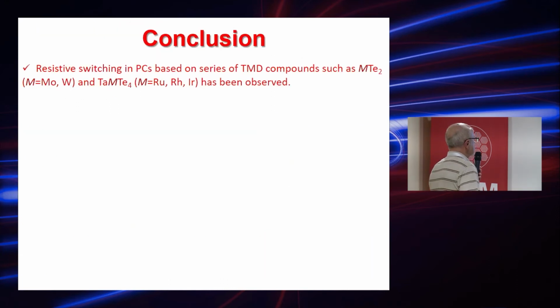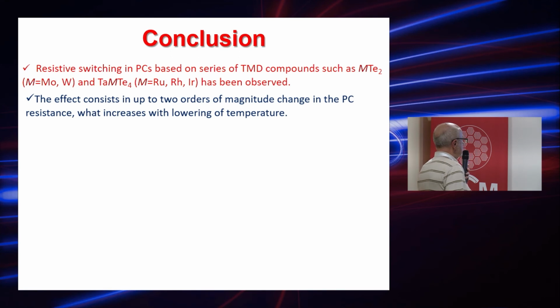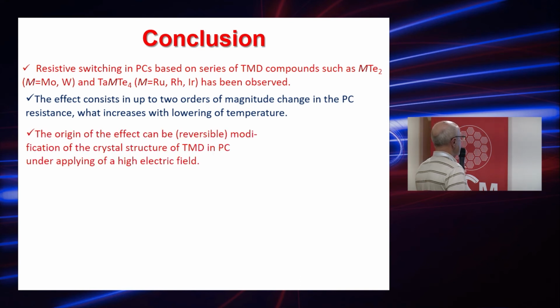So, in conclusion, we observed resistive switching in point contact based on a series of TMD compounds such as molybdenum and tungsten ditelluride and tantalum ruthenium, rhodium, or iridium ditelluride. The effect consists of up to 2 orders of magnitude change in the point contact resistance, which increases with lowering temperature. The origin of the effect can be reversible modification of the crystal structure of TMD in point contact under application